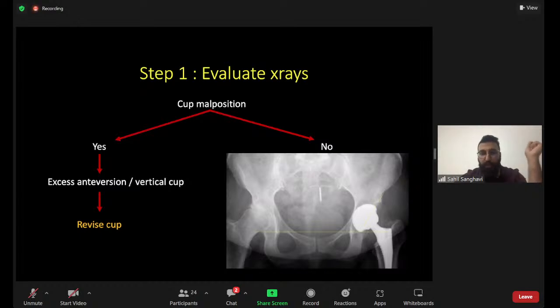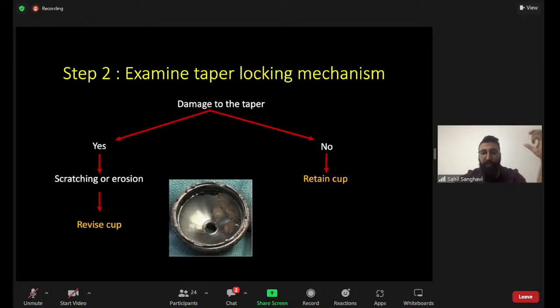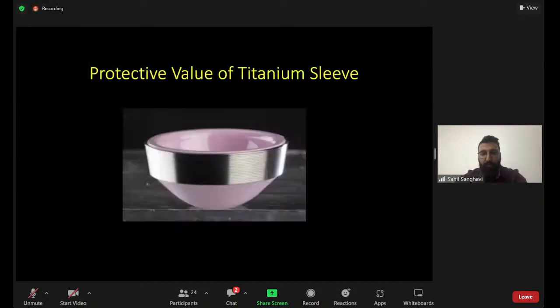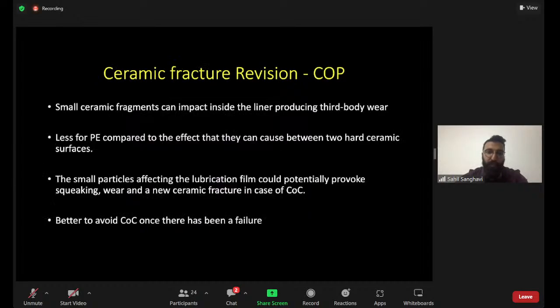If the cup position is good, you have to examine the taper locking of the acetabular shell. If there is no damage and the position is good, you can retain the cup. But if the locking mechanism is damaged, that is, if there is scratching or erosion, you will have to revise the cup. And this is where the protective value of the titanium sleeve on the ceramic rim comes into play.